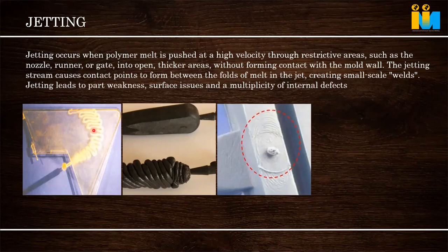And second, we can adjust in the part. In plastic, whenever it is injected into any cavity, it is better that it hits some steel so that it flows gradually and uniformly, instead of suddenly shooting in. This happens generally in a thicker part, thick plastic parts where the thickness is huge, when we are giving a small gate. So instead, give some restriction. People put some ejector pin or projected pin so the plastic hits there, stops its flow and diverts properly. This is how jetting can be solved.